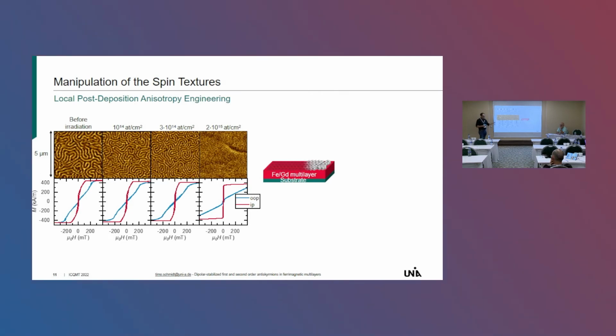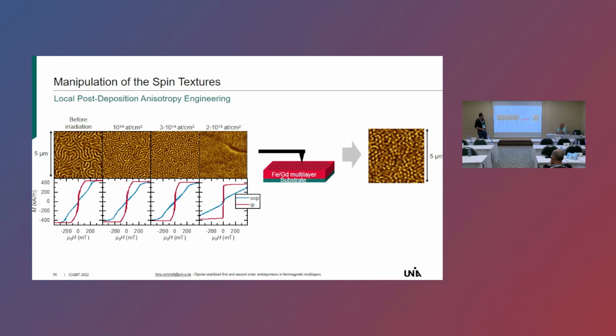So we can remove the nanospheres and then look at it with the MFM. And we really see some round objects here, almost in a hexagonal lattice. It gets a little bit confusing around here, but there are areas where you can really see that hexagonal lattice from the nanospheres.